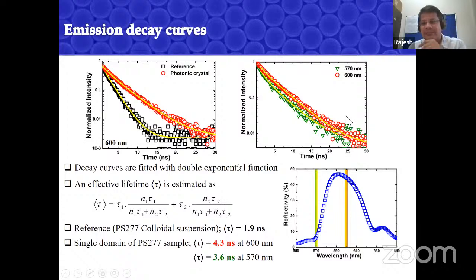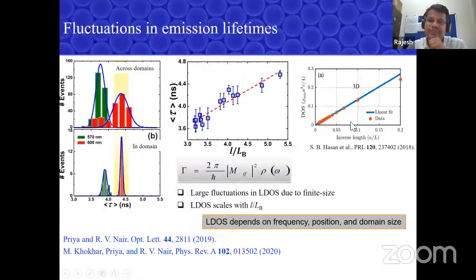So probably I can skip this curve. It's not required for the students, and you don't have time also. And now the question is, do we get the same lifetime everywhere, like intensity? Again, the answer is no. So we measured lifetime at many places on the sample. You can see that it has quite a broad distribution. But within one domain, the lifetime is quite a bit higher within the band gap compared to a wavelength outside the gap.